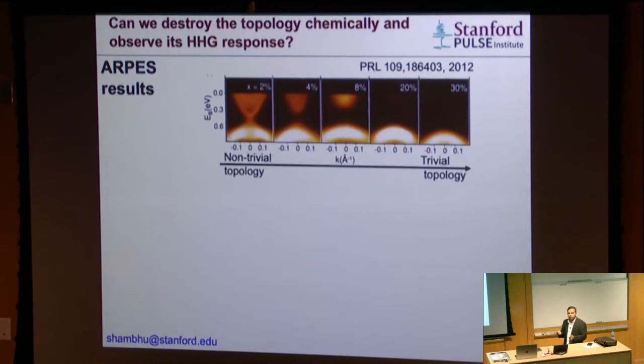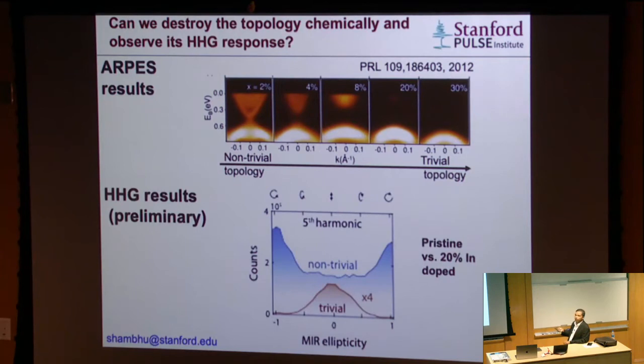Now we are going to do some interesting chemistry here. We change the topology of the material. It's actually our collaborators from Rutgers who did it. They introduced some impurity in the material. This was the experimental, close to pristine sample where there was a Dirac cone to start with. They added some impurities, and at high impurities this Dirac cone disappeared completely. The non-trivial topology is gone. So we take those same samples and do our high harmonic experiment. And here, this was the data. This is the data from the pristine sample.